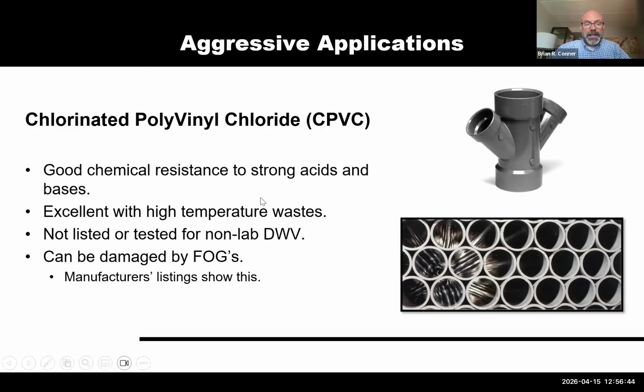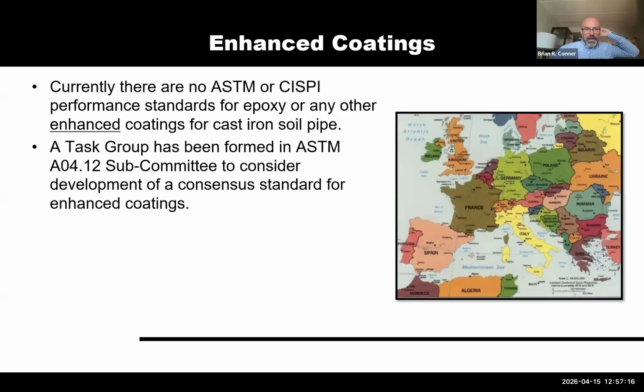And CPVC, while it's great with chemicals, very good with acids and bases, it can be damaged by fats, oils, and greases. So you can't use it in commercial kitchens because most naturally occurring oils are actually stress corrosion cracking agents with CPVC. So you can look at manufacturers like Charlotte Pipe, George Fischer, or Spears, and they actually reference the chemical damage caused by fats, oils, and greases with CPVC pipe. Now, enhanced coated cast iron really is not new.